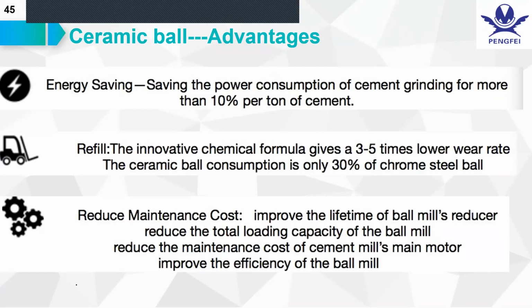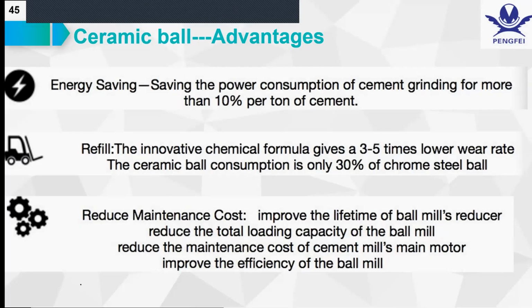And then the second is about good wear rate. The steel ball is about, as I said, 25, even some reach 40 grams per ton. A ceramic ball is about no more than 8 grams. So you can see like 5 times less. So your filling rate every year, maybe you only need 1 or 2 times to fill. And you're going to reduce your maintenance cost and also stoppages, extending your ball mill working hours. Okay, next.